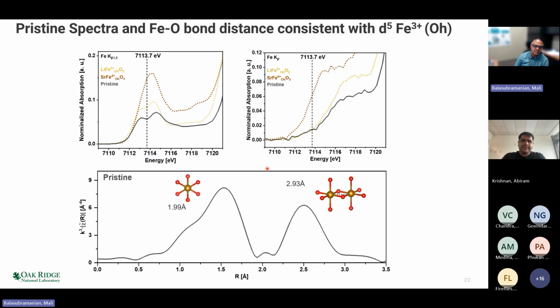the oxidation state and spin state of iron. So here I show you the pristine compound compared with LiFeO2, and this shows the classic doublet, and you get this sort of broad peak at about the same position for this iron in a trivalent state. Now, if you look at the K beta prime, you see that there is no intensity here for the pristine compound. So the pristine compound must be d5 iron 3 plus in an octahedral site. This is also consistent with an expected iron-oxygen bond distance of 1.99 angstrom, and the second shell can be fit to metals present at 2.93 angstrom, which we assign to these edge-shared octahedra.